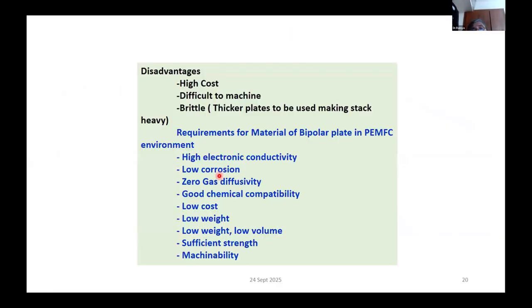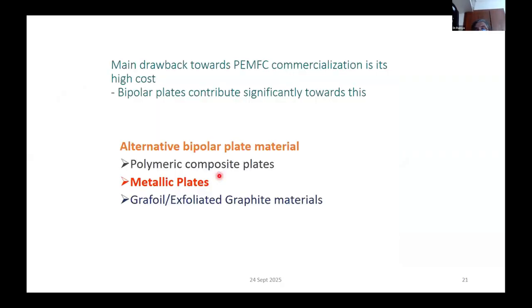One of the major difficulties with graphite is that it is very high cost, and these designs are basically machined. You have to use a CNC milling machine to generate these designs. And graphite is basically brittle. The material properties you are looking at are high electronic conductivity, low corrosion, low gas diffusivity, good chemical compatibility, low cost, low weight, and all that. But like I said, graphite is very expensive.